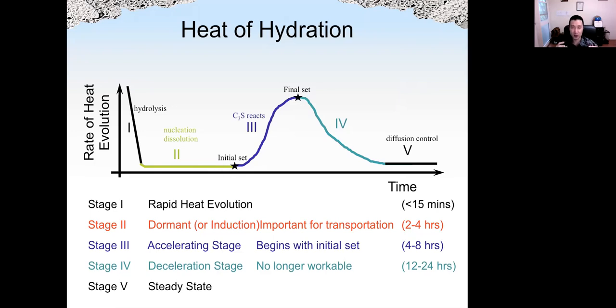The reason for that is because the system needs the concentration of the ions, such as calcium and hydroxide ions, to achieve a certain level. So we call that threshold concentration. Before the threshold concentration is reached, hydration product does not produce too much. So initial set time is the time when the concentration reaches that threshold concentration. So we have more hydration product produced. So the concrete hardens. The hardening begins.